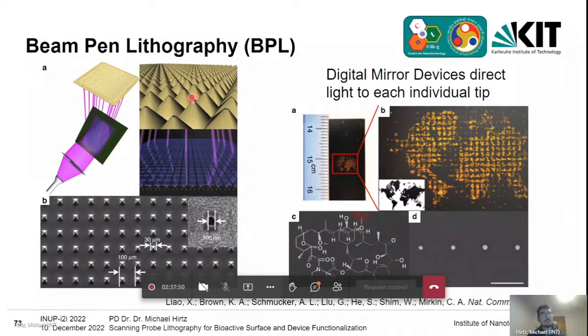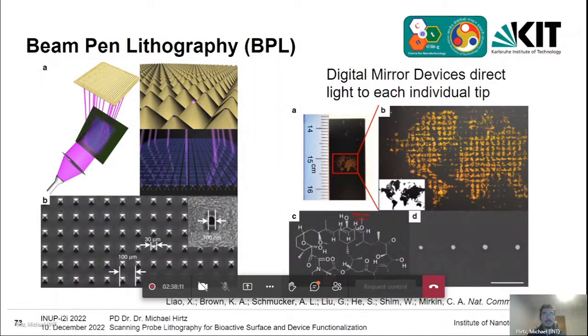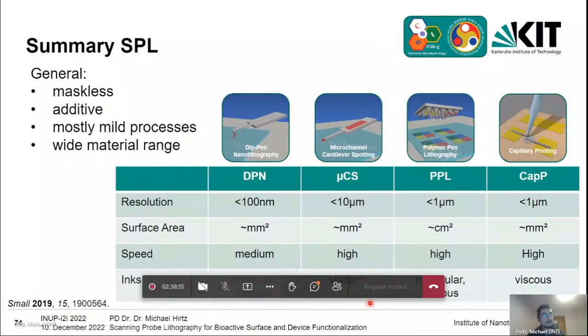And by this, you can turn on and off different light on these pyramids, so different pyramids are on or off in parallel. This allows you, on photoreactive surfaces, to also have large area patterning still with a sub-micron resolution, which is also demonstrated here from the Mirkin group for chemical formulas in form of this world map. So with this, I come to my summary.